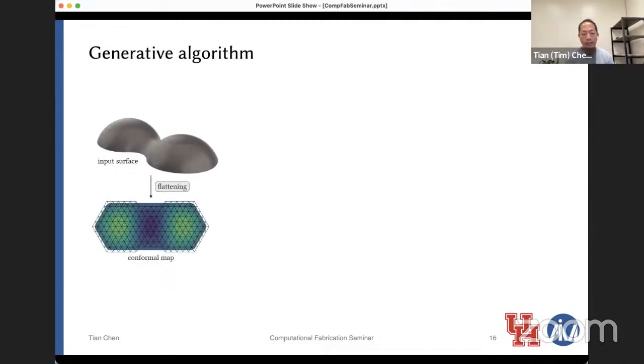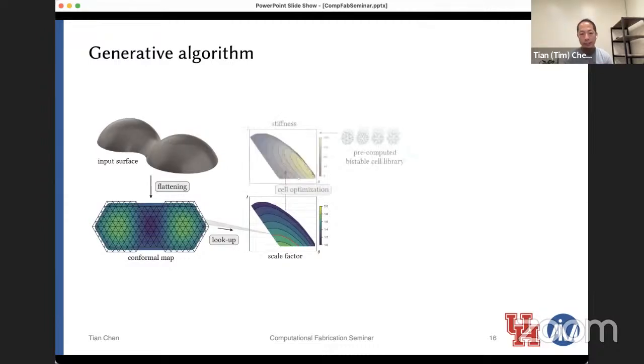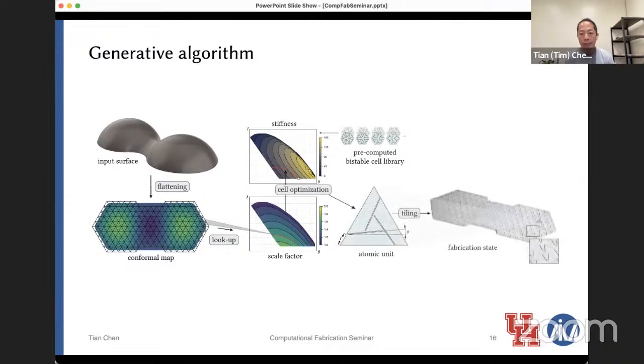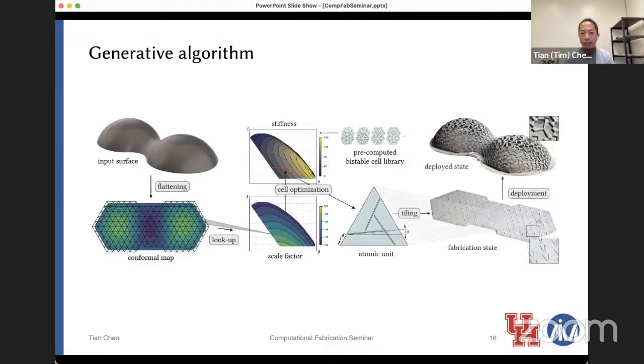So we have a generative algorithm in mind. Given an input surface, we first calculate the conformal factor that allows us to flatten it into the planar state. In this case, I'm using light green for a lot of expansion and blue for almost zero expansion. Then we look up in our pre-computed table to find the parameters that give us that particular scale factor. From these parameter combinations, we find the unit cell that has the stiffest behavior. Then we tile them back into the planar state with the different parameters, triangles tiled together, and then we can easily deploy this into the 3D state.